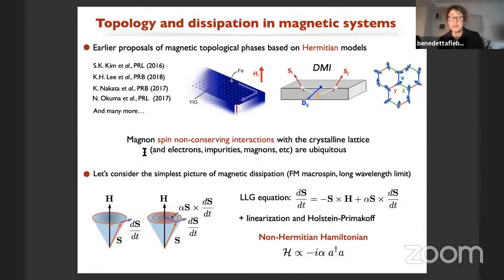We can simply use the Landau-Lifshitz-Gilbert equation, which states that the dynamics of a spin will depend on the effective field that is applied on the spin, but will also depend on a term that breaks time reversal symmetry since it's dissipative. And this term depends on a dimensionless parameter that is called Gilbert damping.